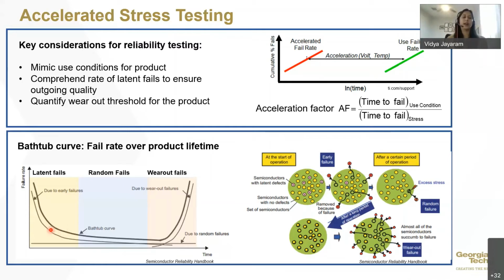After that point, you would see the curve stabilizing a little bit, where now that all of the yield related failures are weeded out, the failures are more consistent, where all of the units behave in a similar manner after some long period of operation. After a certain point, we reach the wear out region, where you would see multiple failures occurring for most of the parts that were tested, since this is when your package, based on the process, the material, the architecture system that you have set up, is finally starting to wear out. So this would be a typical bathtub curve fail rate prediction over time that you would see for any kind of